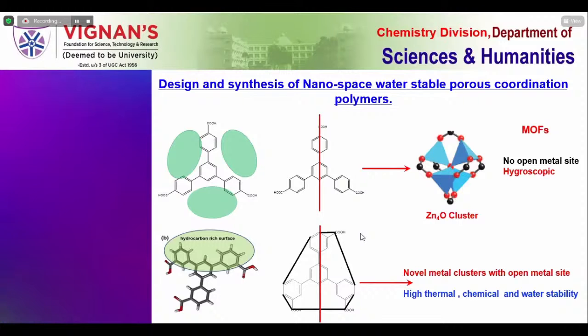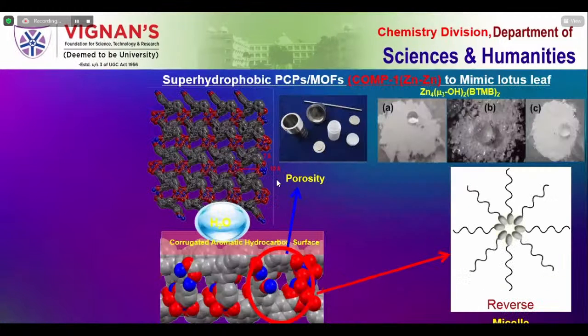It's entirely different from the previous structure we got, because they are highly symmetric in nature. Even though the porosity is not very big, very small porosity, maybe only 8 by 10 aperture, what is very important is that as per our expectations we were expecting a hydrophobic material, but to our surprise, it even becomes super hydrophobic. What is the meaning of super hydrophobic? I will tell you in the coming slide. Hydrophobic and super hydrophobic materials I will be explaining with the introduction.